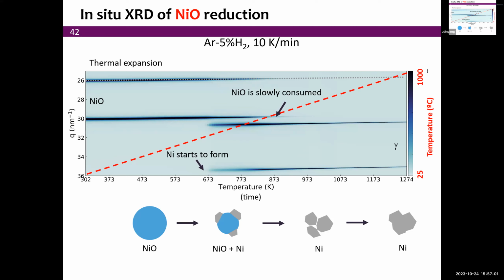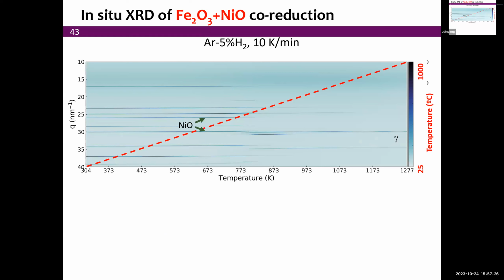And as the grain coarsens, we see that this very broad diffraction peak, which is visible through that kind of fuzzy diffraction, becomes finer and finer, indicating that we have much larger grains as compared to the sub-micron grains that we had before. And so that's relatively straightforward. We go from nickel oxide to nickel with some overlap between the reactions.